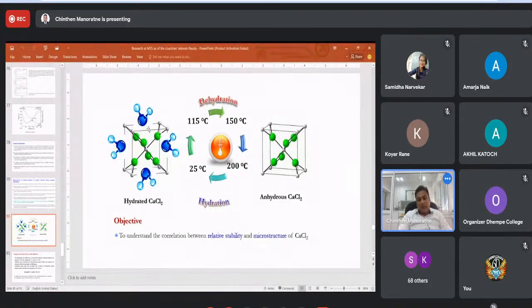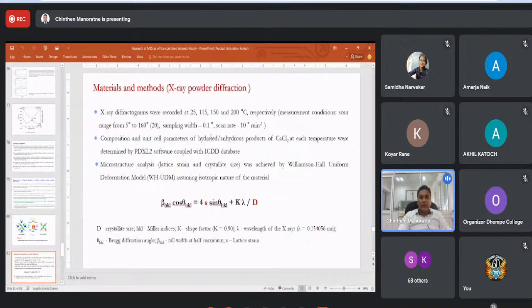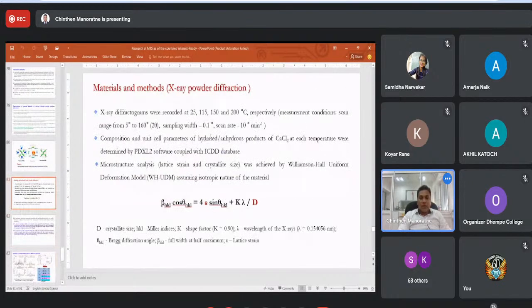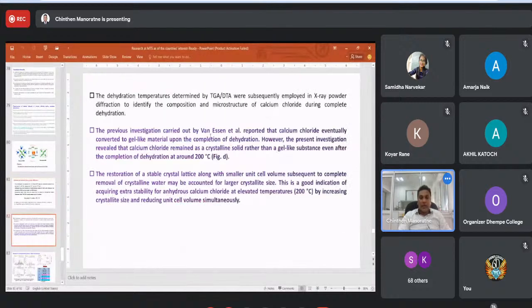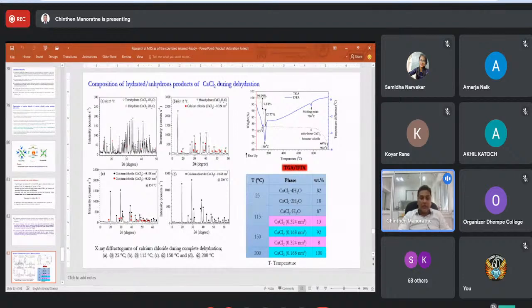This is the normal hydrated calcium chloride, and this is anhydrous calcium chloride, without water. We studied these at different temperatures using XRD, and there also we observed their microstrain, how they behave, and the corresponding microstructure. Now you can see the XRD spectra for calcium chloride at room temperature and elevated temperatures like 150, and the gradual conversion of hydrated calcium chloride to anhydrous calcium chloride.